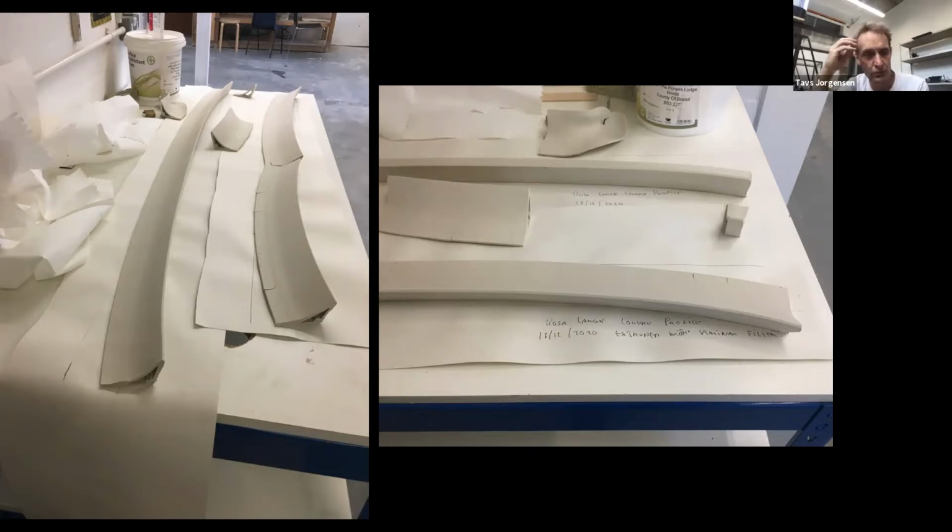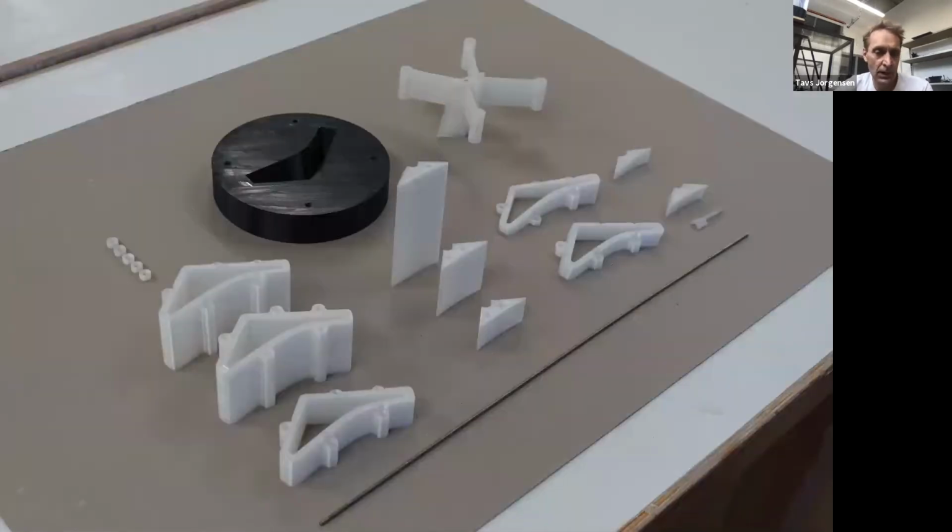It is what industry is really concerned about. It's a bit like the dark art in the industry, to make sure that you can extrude straight, and it's called balancing the die, so that it's extruding at the same rate throughout the die, and you're not forcing clay into one area more than the other. The way that we try to fix or explore that is partly through discussions with Damien and others, but also just testing to see how you can manipulate the clay in the die. And this is some of the tests we do, like a kit to explore it and see how we can balance the clay flow in the die.